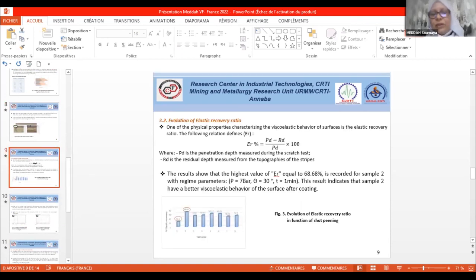And for the evolution of the elastic recovery ratio, shown by the following relation, where PD is the penetration depth measured during the scratch test, and RD is the residual depth measured from the topography of the stripe. The results show that the highest value of the recovery ratio, equal to 68.68%, is recorded for sample 2 with process parameters pressure equal to 7 bar, theta equal to 30 degrees, and time equal to 1 minute. This result indicates that sample 2 has a better viscoelastic behavior of the surface after coating.